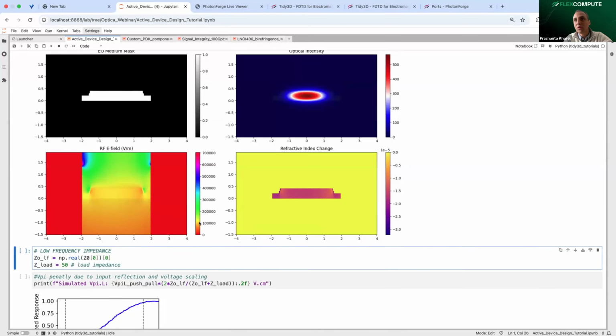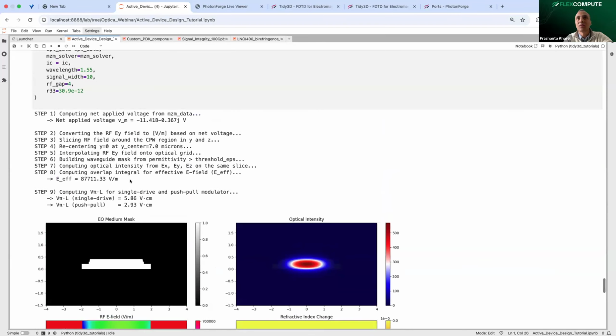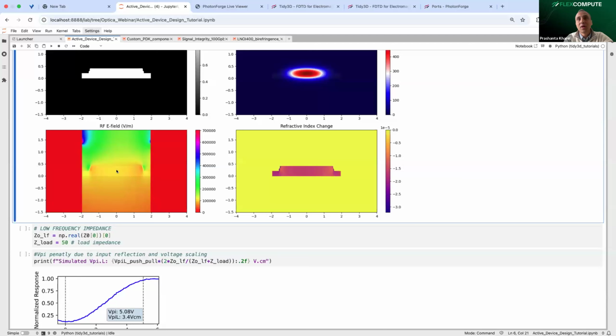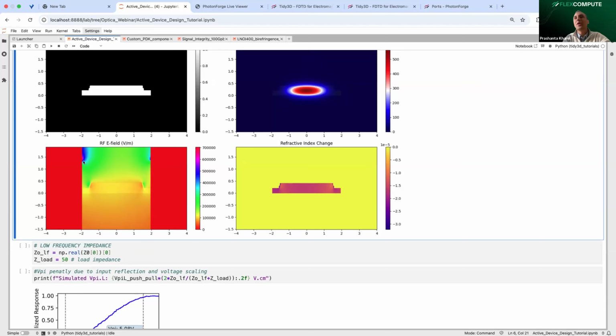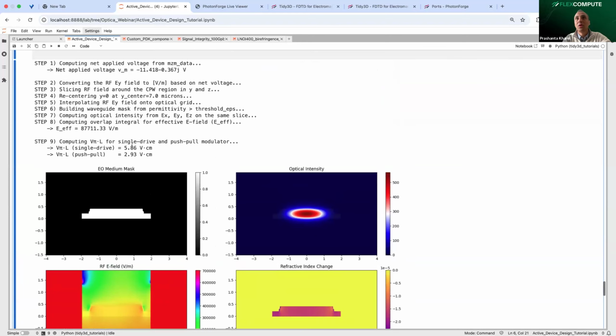We calculated what this is. On average, it's around 8.8 times 10 to the power 4. So there's this reduction in electric field because this is a high dielectric constant material, and this is also what leads to reduced V-pi-L. This is why you need to design your electrodes and where you place them and how wide the waveguide is and all this stuff, so that you can get to a low V-pi-L for your modulators.